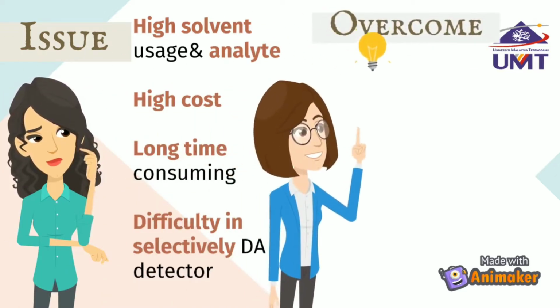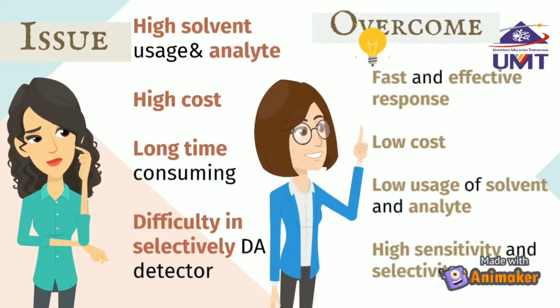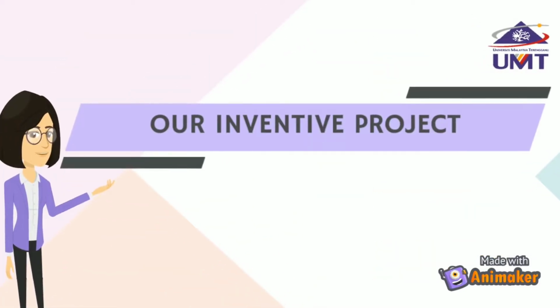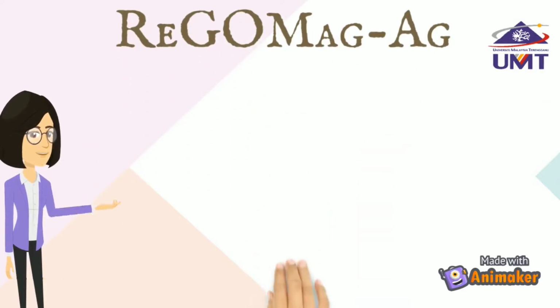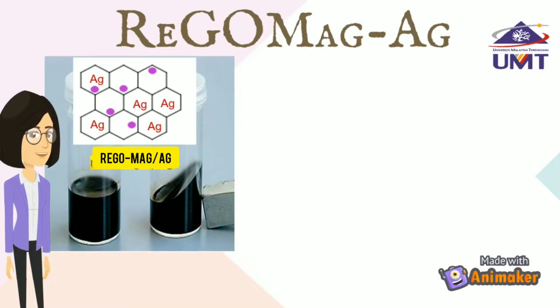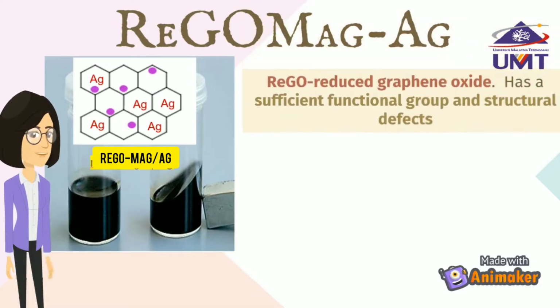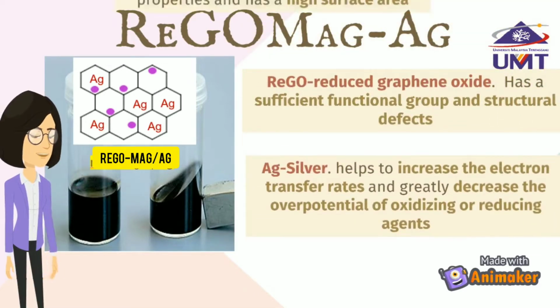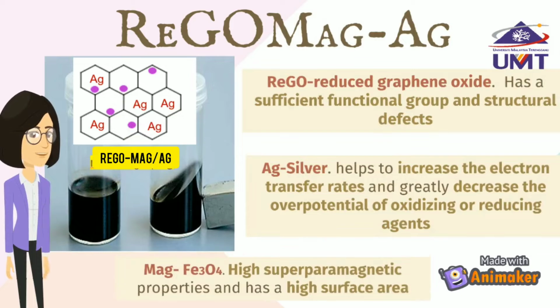Hence, to overcome this problem, a dopamine sensor with fast and effective response, low cost and high sensitivity and selectivity must be innovated. Therefore, to solve this issue, we came up with an idea for this project, a highly sensitive and affordable reduced graphene oxide magnetite silver dopamine sensor. The materials chosen exhibit good characteristics to increase the sensitivity and selectivity of the dopamine sensor with an easy and simple method.